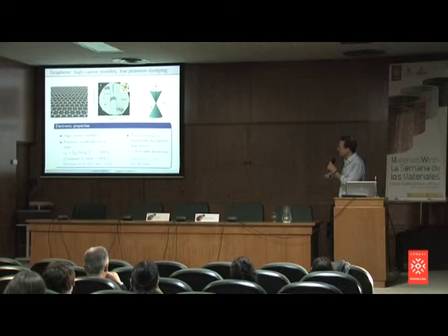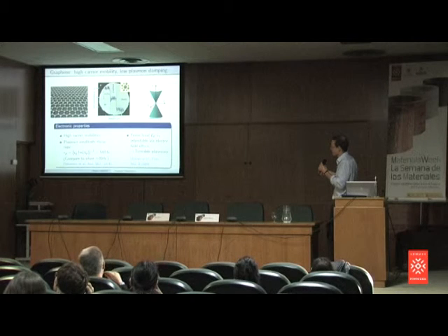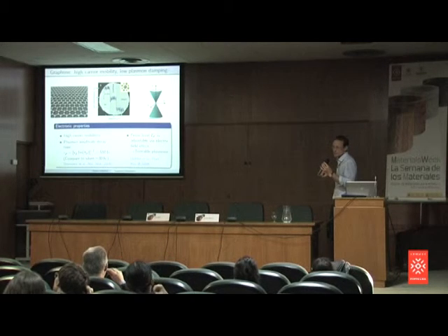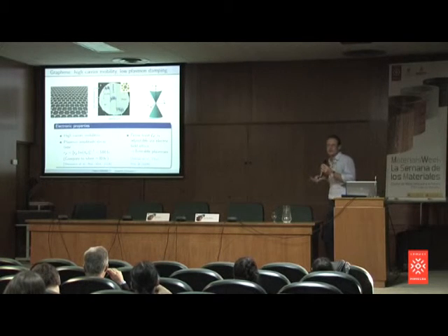And, well, they measured, let's say, typical decay times for plasmon oscillations in graphene. They can make very good samples. These are special samples. Okay, this is encapsulated graphene in boron nitride. But whatever, what they get is a number, 500 femtoseconds, and this doesn't tell much. But if you compare this to how long a plasmon lives in silver, for example, this is one order of magnitude smaller. So we get a factor of 10 here in the plasmon lifetime. Okay, this is one thing that graphene can do for us in plasmonics.